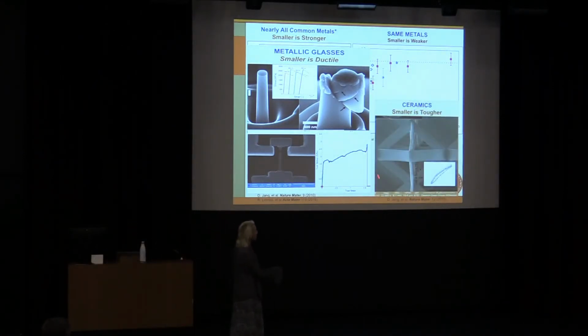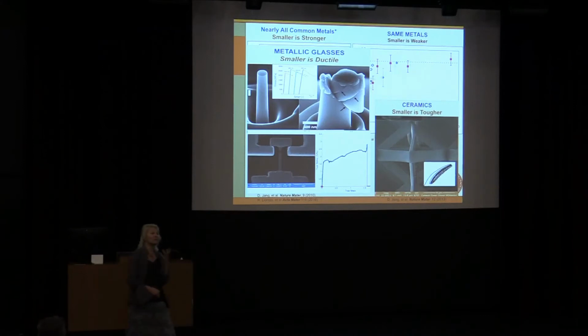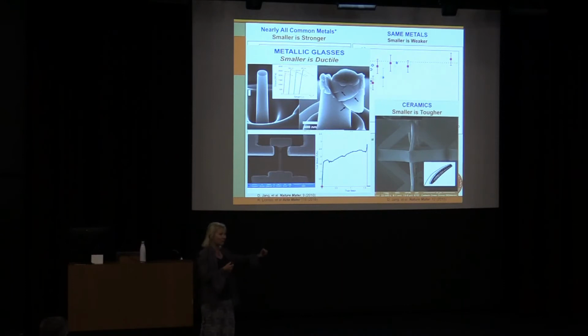So this is a ceramic nanotruss, and this is a single unit cell. And we're going to compress it now. And watch what happens to these outer beams. They're slightly elliptical, and so they're bending. Imagine bending a piece of chalk. You're not going to be able to. It'll snap. But this is ceramic titanium nitride. This nitride nanolattice, first of all, each beam is deflecting so much that the tensile stress here is something like 1.7 GPa. Ceramics are not supposed to stay intact when you apply 1.7 GPa of tension onto them. But these are staying intact over multiple cycles.